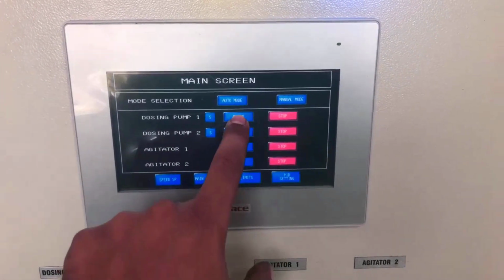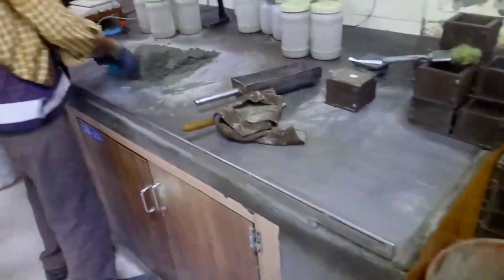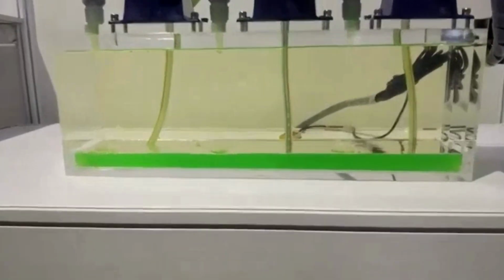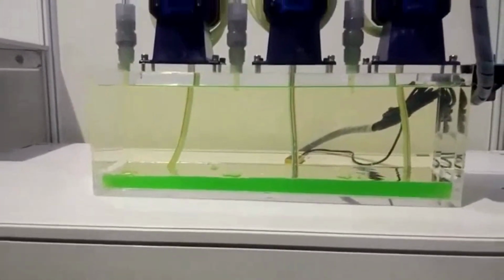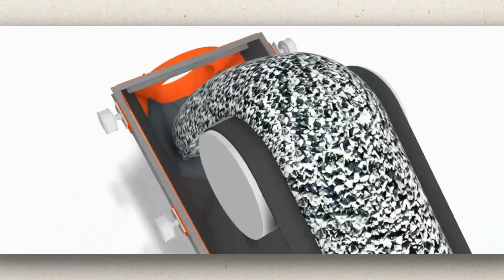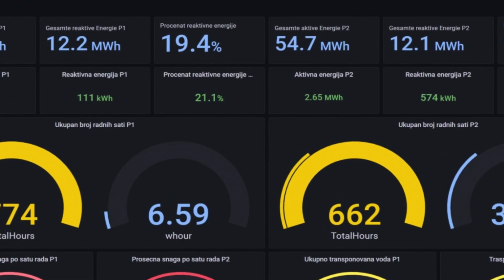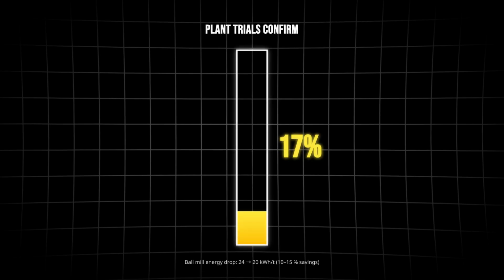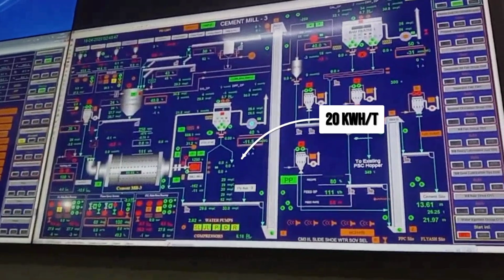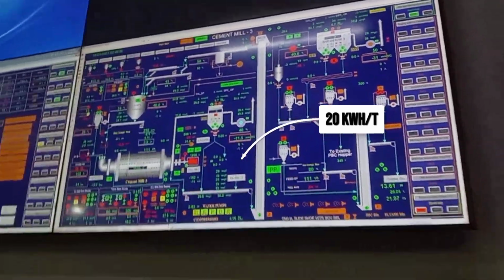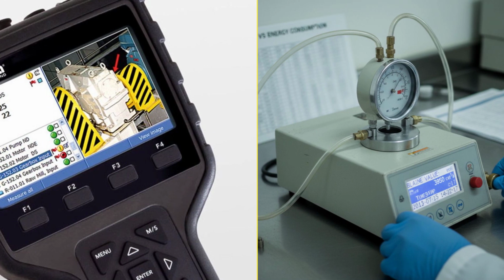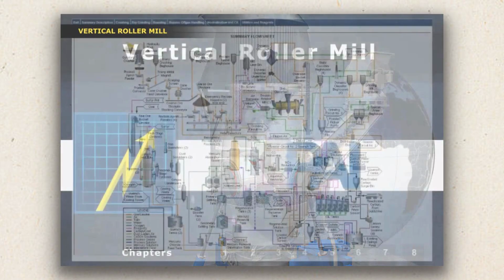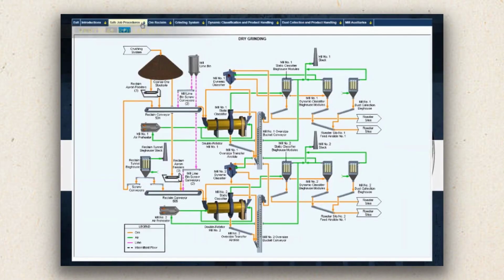Grinding aids like triethanolamine and triisopropanolamine have become essential tools in this calculus. Dosed at fractions of a percent, these additives coat cement particles, break up agglomerates, and smooth flow through the mill. The result is a measurable drop in energy use. Plant trials confirm savings of 10 to 15%, with specific energy in ball mills falling from 24 to as low as 20 kilowatt hours per ton. In vertical roller mills, savings are slightly lower but still significant, often enabling a 200-point increase in Blaine for less than 1 kilowatt hour of additional energy.